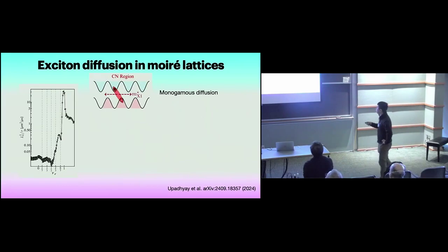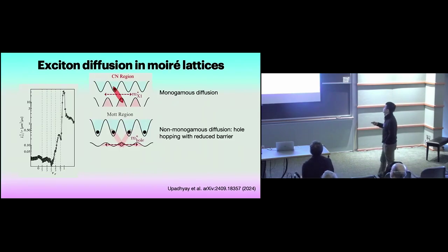In the neutral exciton, neutral charge regime, the exciton diffuses as a collective particle, right? We call this monogamous diffusion, so the electron and hole move together. But when you fill the Mott insulator state, there is one electron per lattice site. Here, because what Ajit talks about is an interlayer Moiré exciton, the location of the electron is actually slightly mismatched from the location of the holes. So you form an exciton like this. It has a slight mismatch in real space.